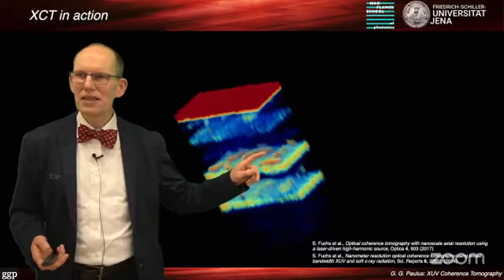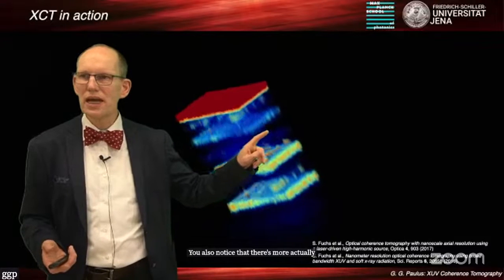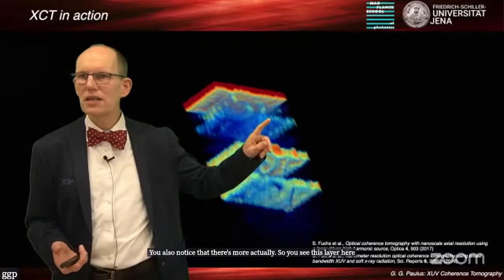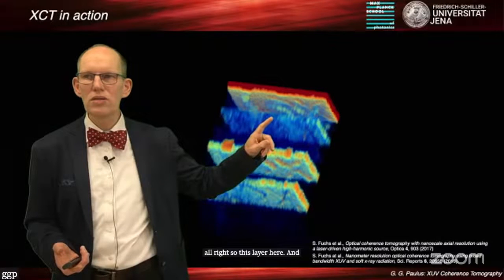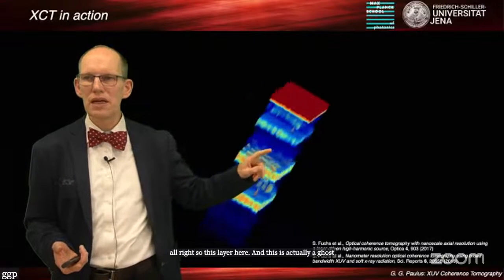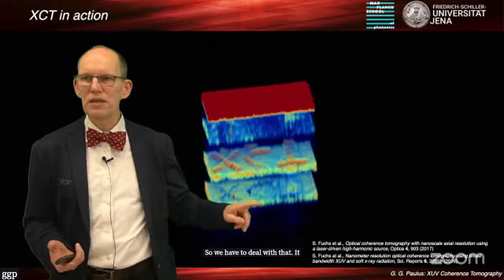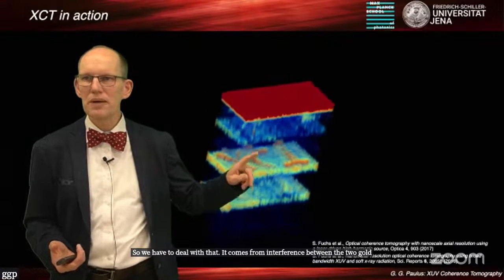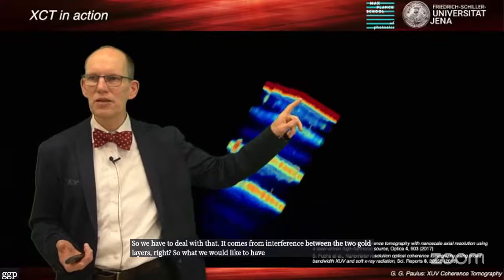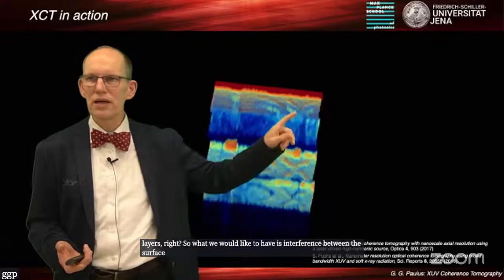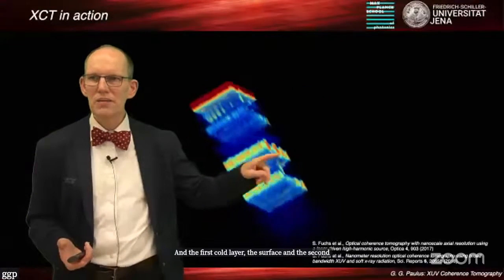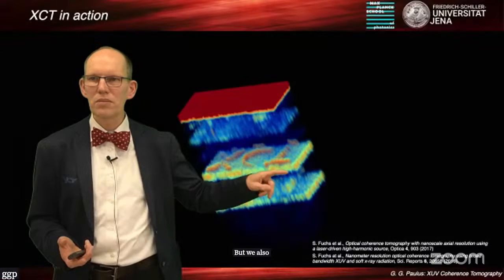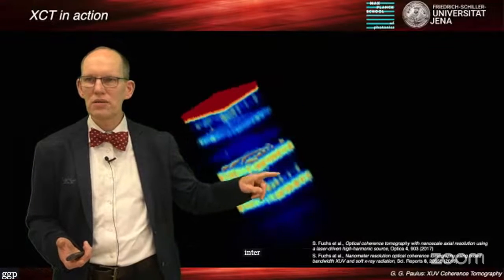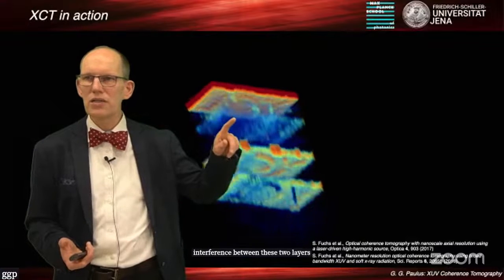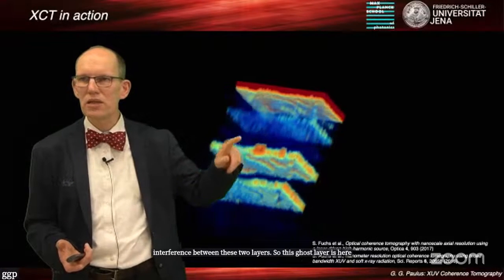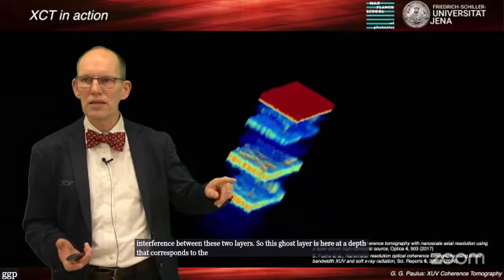You also notice that there's actually more. You see this layer here, right? This layer here is actually a ghost, so we have to deal with that. It comes from interference between the two gold layers. What we would like to have is interference between the surface and the first gold layer, and the surface and the second. But we also see a signature from interference between these two layers. So this ghost layer is at a depth that corresponds to the distance of these two gold layers.